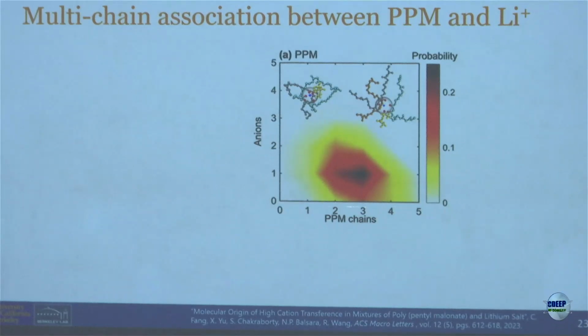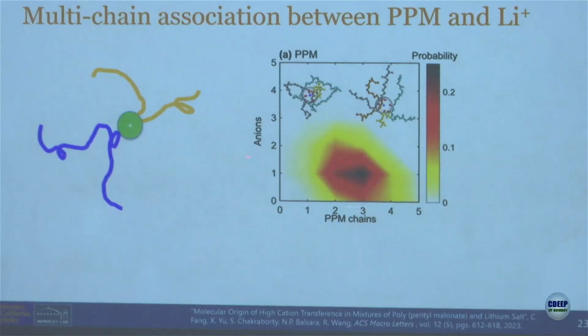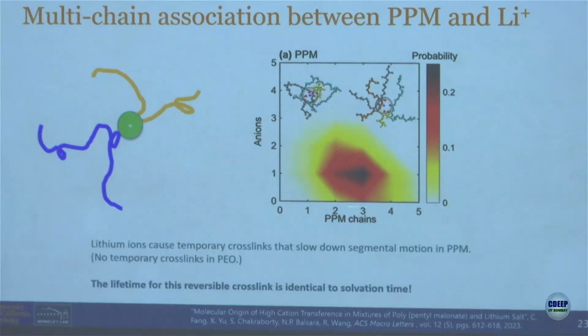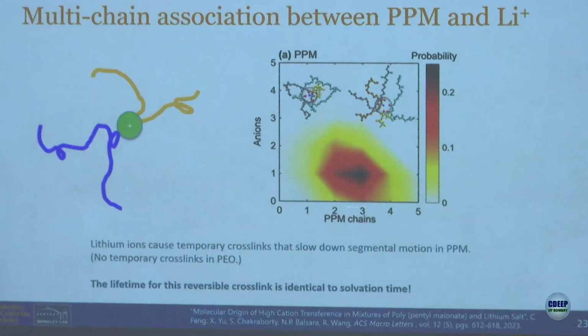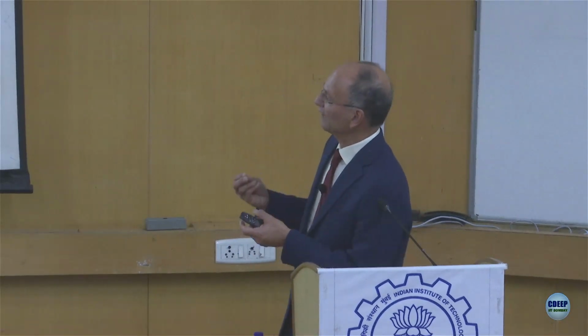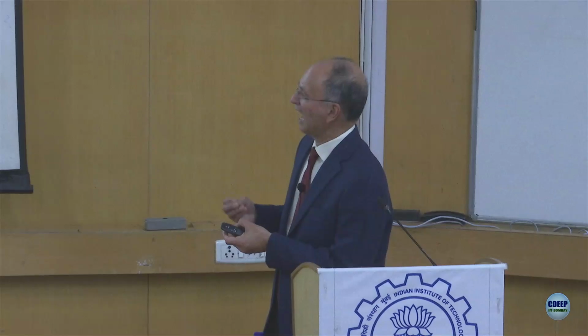Much more complex and somewhat ugly, whereas the pyramid is nice and simple. This is very ugly. It looks like a cockroach or something. But this picture suggests that the cation is at least connected to 2 chains. And this is to me very interesting, because that means the ion is making temporary crosslinks. And those of you who work in polymer science will know that there's a huge literature on temporary crosslinks, hydrogels, and things like that, where the crosslinks come and dissipate. And so this is a connection between polymer physics and electrochemistry.